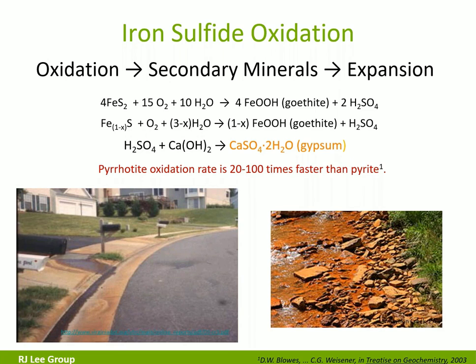So when you're talking about having these minerals in aggregate and concrete, the oxidation again creates sulfuric acid. That is going to react with the concrete, the paste in the concrete, and form some secondary minerals, ettringite, gypsum. These are expansive. They also will decrease the pH. And you'll get cracking, and in the